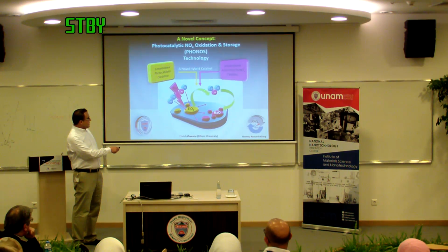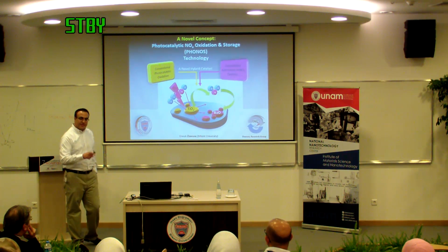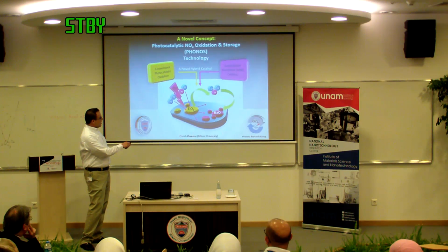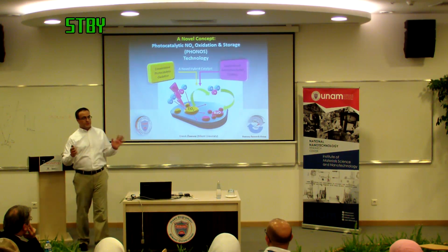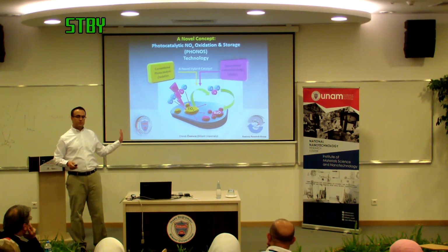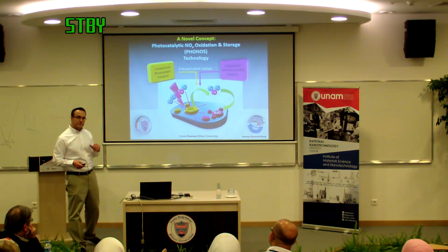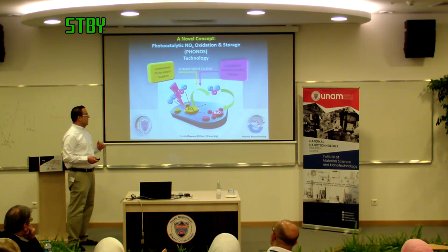So you can oxidize this to NO2, and if you can capture it in solid state without letting it slip through to the air, it is a very risky business, because there is some chance that while we're trying to clean the air, we might intoxicate the air. But if you can manage that, if you can oxidize rather than reduce, because reduction, forget about it. Forming the double or triple nitrogen bond at room temperature with high efficiency has not been demonstrated.